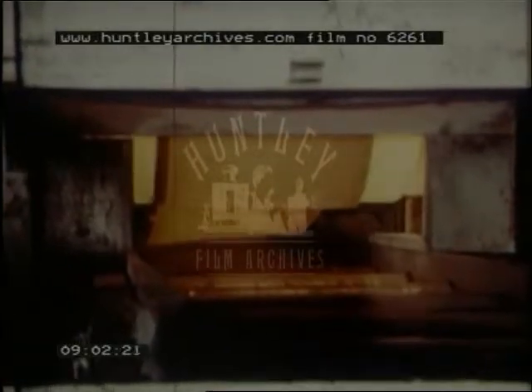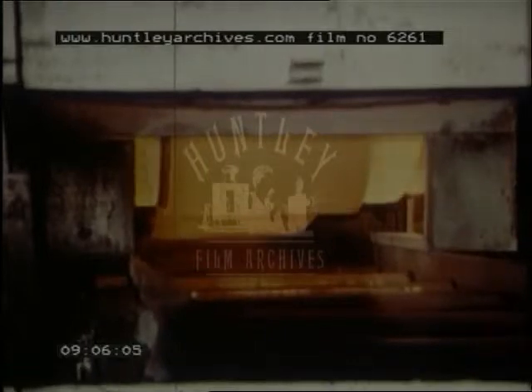A short tour of the continuous sheet mills at our subsidiary company, Sheffield Rolling Mills Limited, illustrates our ability to deal with such demands. Slabs 5.5 inches thick are first rolled in a hot reversing mill. This is followed by rolling in a fast hot Steckel mill, where, during passes through the rolls, the strip is alternately coiled in reheating furnaces situated at either side of the mill. These furnaces maintain the temperature of the strip necessary to reduce it to 3/16 of an inch in thickness. The stainless steel is now in wide strip form and is coiled ready for further processing.